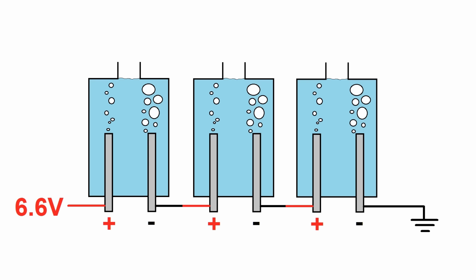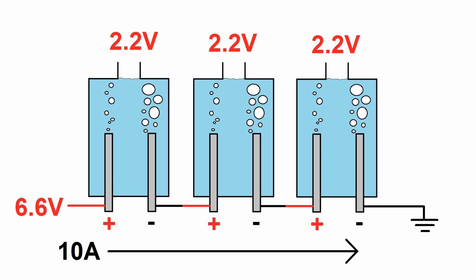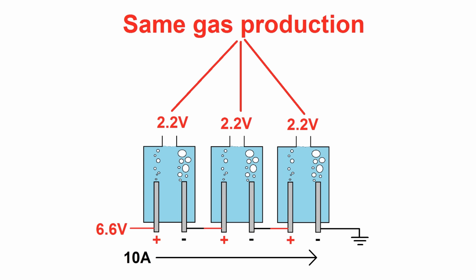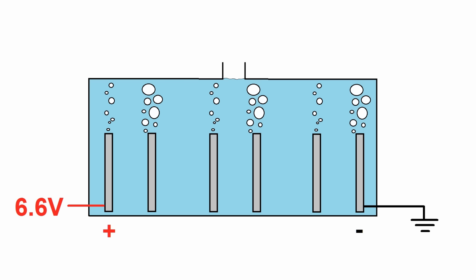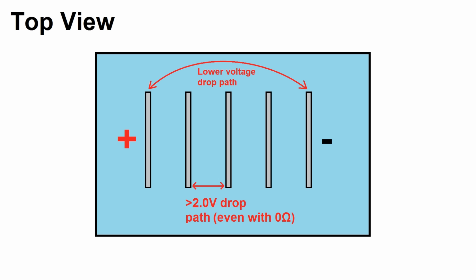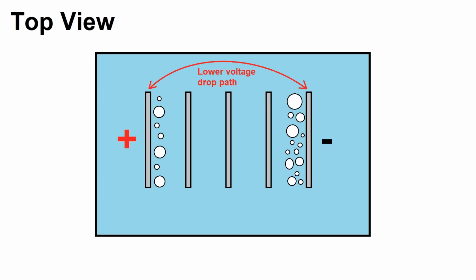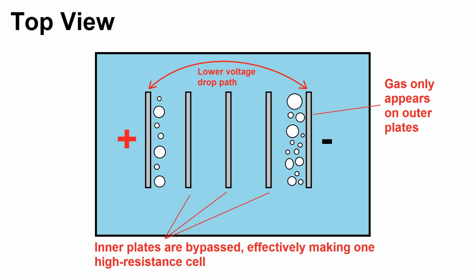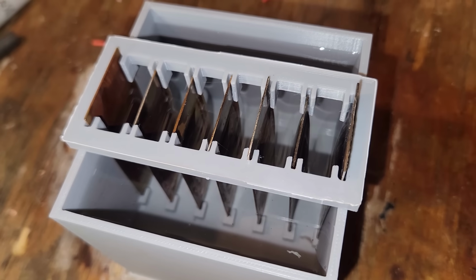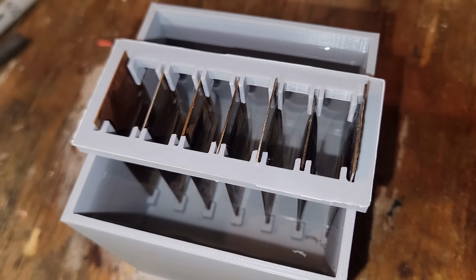If all your cells are physically separate, the voltage of your power supply would be evenly divided between the cells and they'd all be producing the same amount of gas. But when you just shove the whole plate stack in an electrolyte bath and turn on the power, that's not what happens. This is because the current has the option to simply bypass the inner cells rather than passing through them. If the resistive voltage across the section of electrolyte is less than the 2 to 2.5 volt drop across this cell, it's just going to bypass it altogether, so the only plates that are actually producing any gas are the very outer ones. Here's a small example with 6 cells that have a large amount of space on either side that current could flow through.